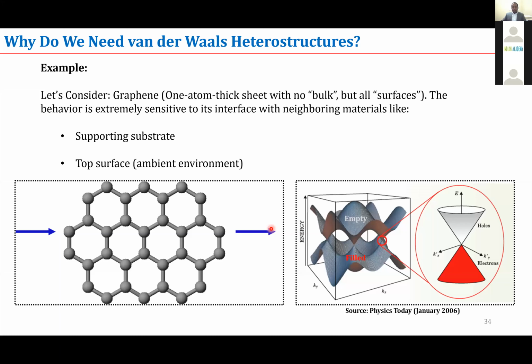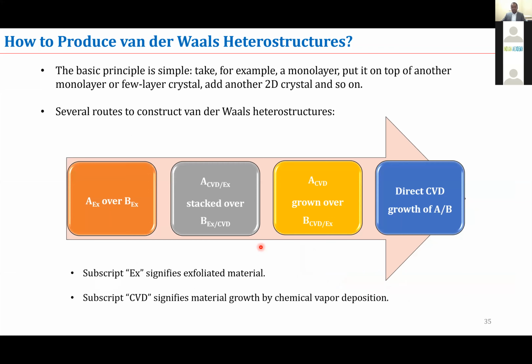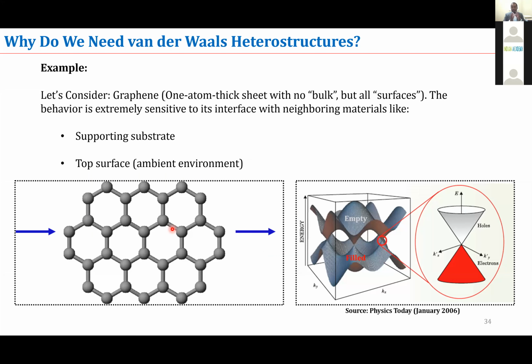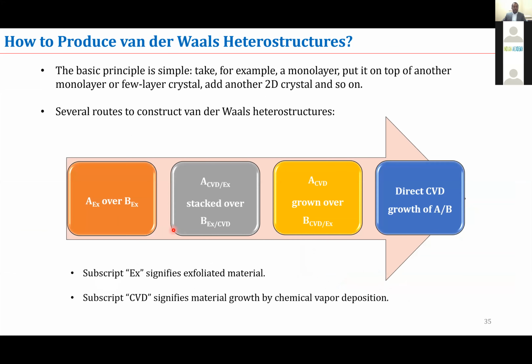So it is important to sandwich the structure. It is important to create heterostructures to protect graphene from external influence. For example, any oxygen atoms or hydrogen atoms that can come and sit on graphene will drastically influence its electrical conductivity. Electrical conductivity can be reduced by many orders of magnitude if you have a single defect on top of graphene. So how do we create heterostructures, and what materials will be suitable for graphene? That is what I am going to discuss now.